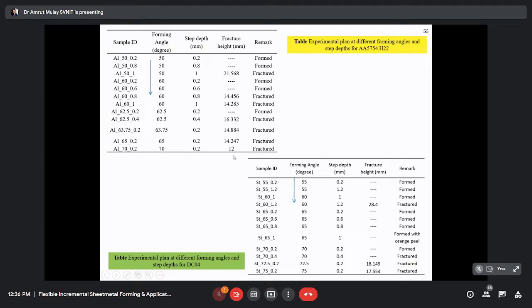And if you go down, you can see that even at 63.75 forming angle, even when the step depth is 0.2, you received a fracture. You received a fracture height. The fracture height is 14.884, and it is fractured. So that's what I would like to tell you, that the fracturing of a material is very important. And up to what maximum extent you can speed up the process of forming, that is also very important.